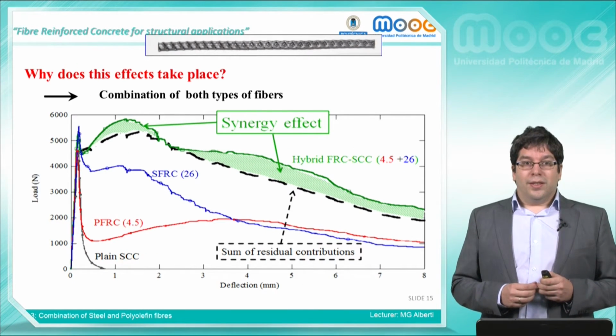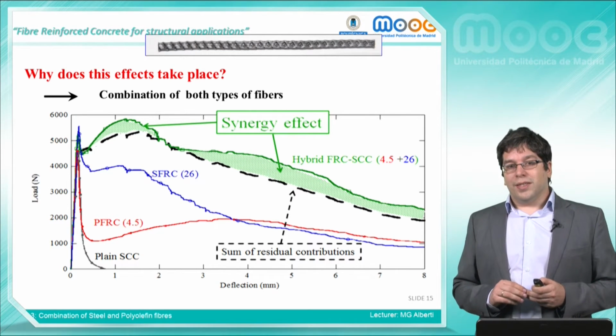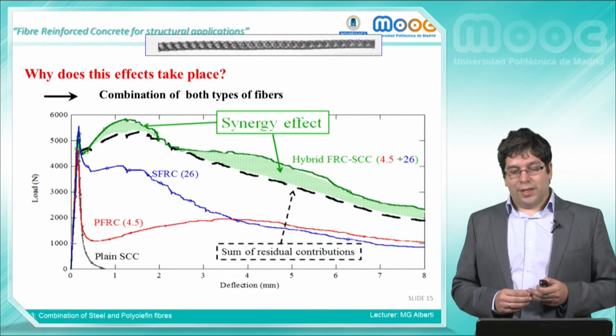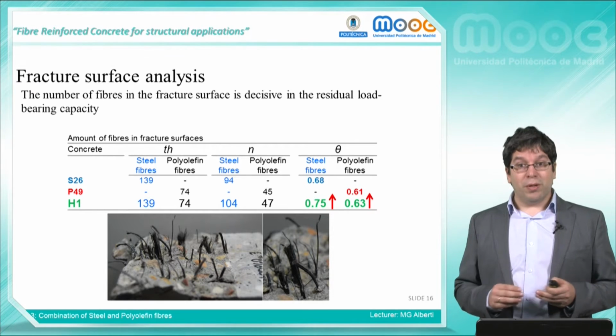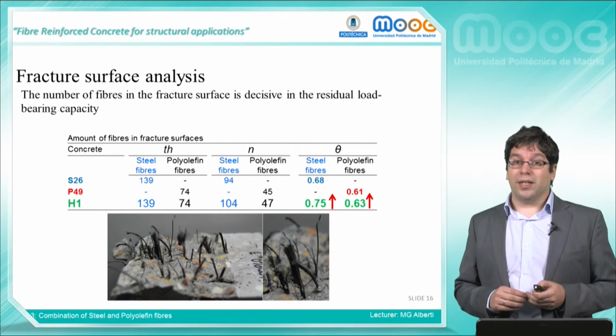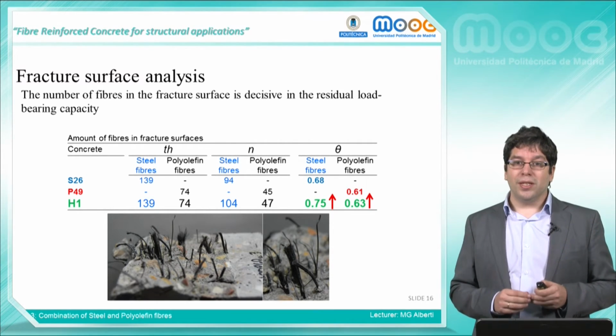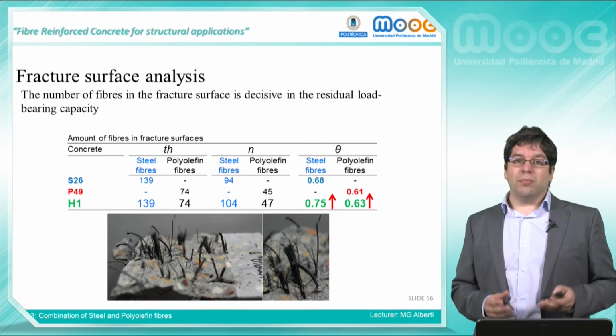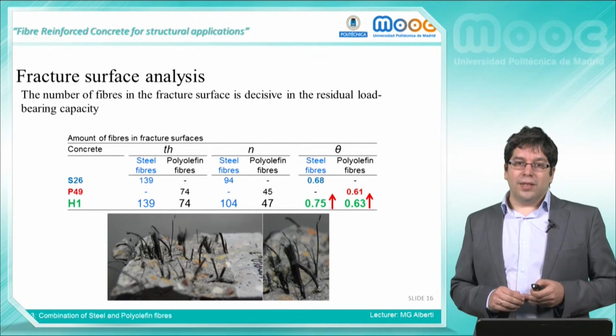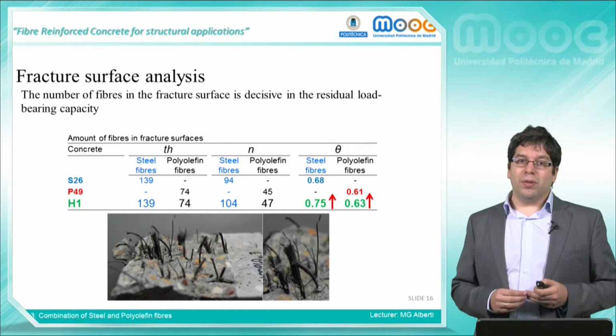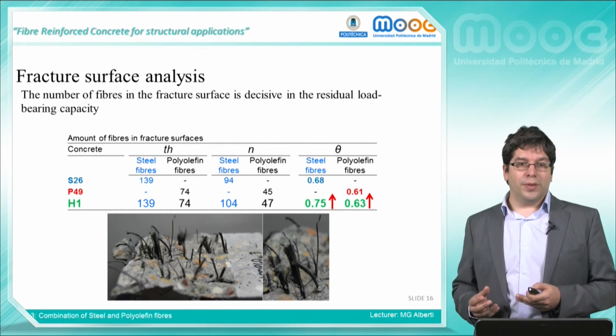So the question appearing was, why does this effect take place? Thus, this had to be explained by means of a fracture surface analysis in which results could be seen that both types of fiber improved their orientation factor. That is to say, the synergies were explained because each fiber type improved the positioning of the other.